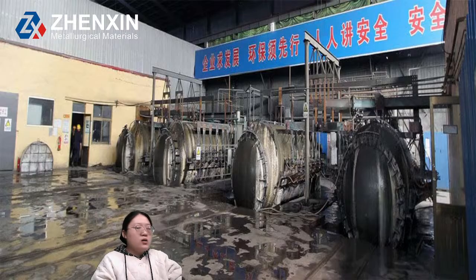Use the rare earth nodulizer when sulfur is high, the section is thick, and the casting geometry is complex. But the non-rare earth nodulizer is better when the base iron is clean, for thin wall castings, and fast production.